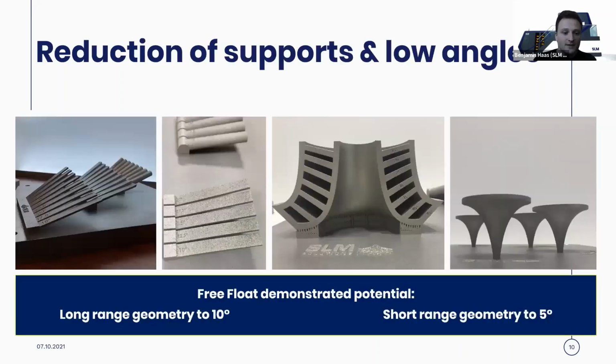Some more examples. So I already showed you this part on the first slide. Now I guess it's a little easier to see that we're testing three different geometries here. And that was, as I said, in 2018. And just a year later, in 2019, it was still a development program, but we showed the world that we had now reduced that value from 15 degrees to just 10 degrees. And by doing that, we also tested a few other things.